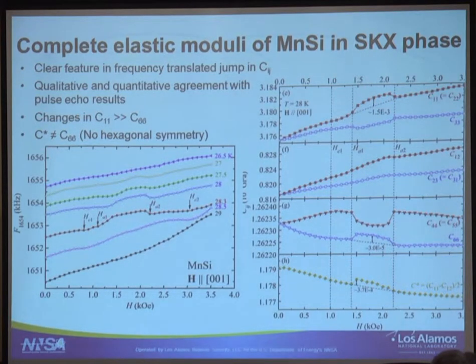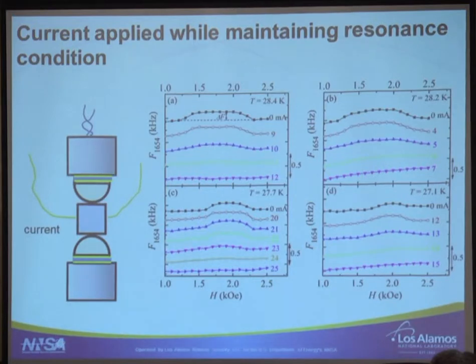We can go even further, and now we put current at the same time that we measure the resonance. So Yang was able to put leads and put current and not destroy everything, and at the same time being able to track the frequencies. So here I'm showing the C11 frequency. It's 93% C11, and what we did is track the jump, the stiffening jump, delta F, at different temperatures for different currents. So here, let's go at zero current.